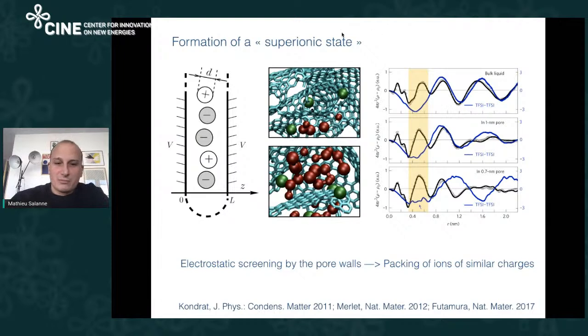So this was a theoretical model, which was published in 2011. And in 2012, our molecular simulation gave really similar things. Here you have at the top a snapshot from a positive electrode, and you have some anions that are packed together inside a carbon nanotube. At the bottom, you have a larger pore that you can see is filled with cations. So you really have this kind of superionic arrangement.